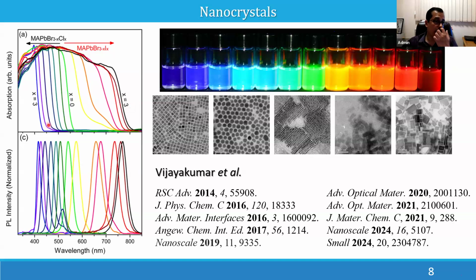For example, if X is chloride, all three anions are chloride. In that case, we will get an absorption like this. It is slightly below 400 nanometers, and emission is slightly above 400 nanometers. It is purely blue to violet color. When you start replacing the chloride with bromide, here it is all chloride, and in the next stage, you have two chloride and one bromide. You will slightly shift the spectrum to here. Then you have one chloride, two bromide. Further, you can shift slightly into the red region.